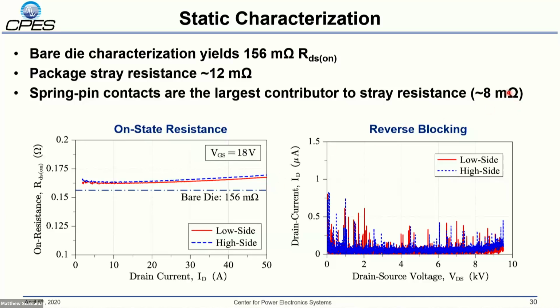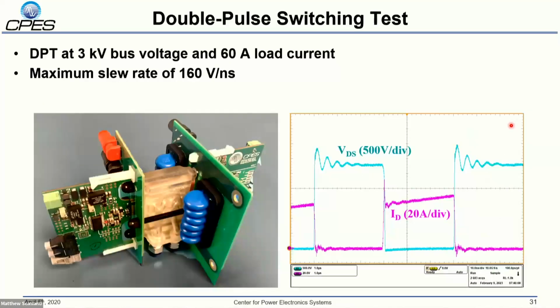And what I found is that we're picking up about 8 milliohms from the spring pins. This is probably the largest contributor to the stray resistance, and probably the biggest area that we could improve this if we wanted to get this number down further. One of the constraints I had to operate in was using a commercial off-the-shelf spring pin. So if we open up the door to custom spring pins, larger diameters, stiffer springs, this is hopefully a number we could get down. The last thing I'll highlight here is some double pulse switching tests that we did.